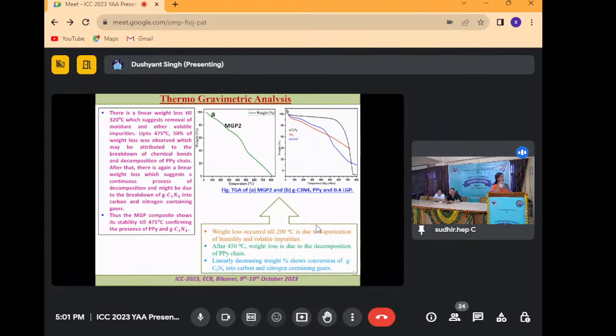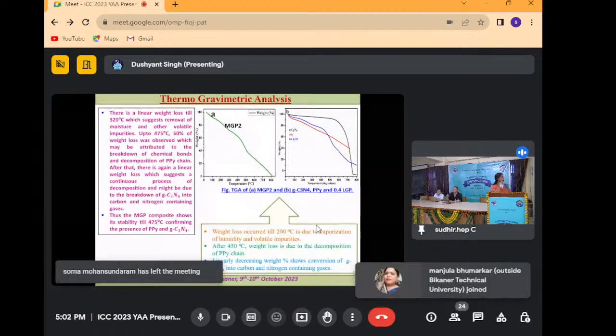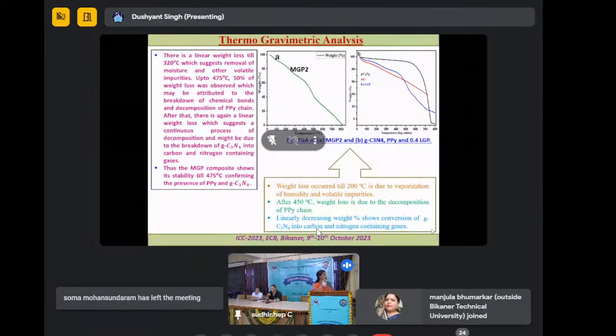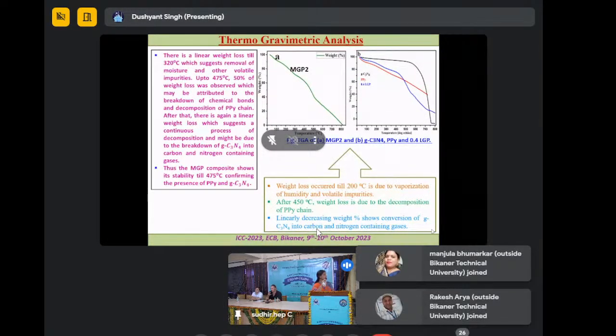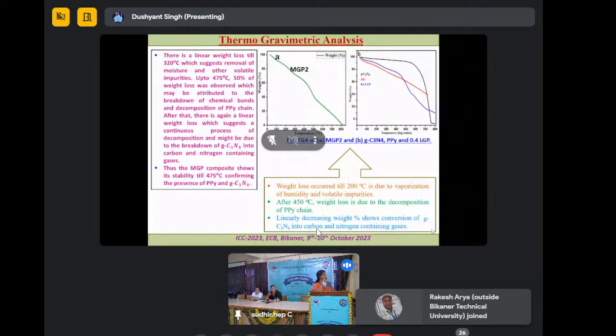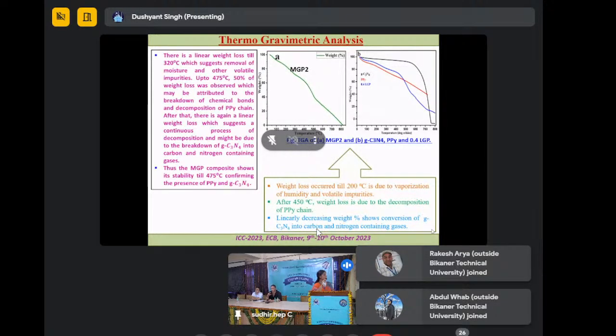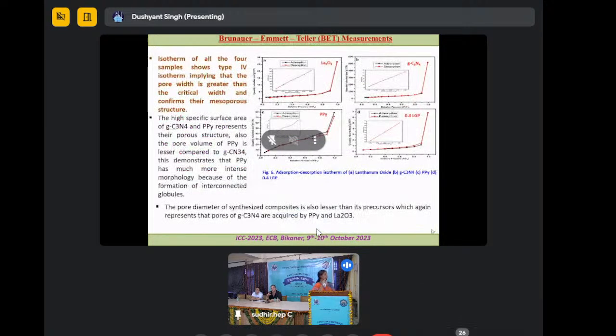And these are the TGA results, which show the thermal stability of these nanocomposites, how and at what temperature LGP and MgP are thermally stable. So weight loss occurs till 200 degrees centigrade in LGP nanocomposites. In graph B we can see that after 450 degrees centigrade weight loss is due to the decomposition of the polypyrrole chain. And in the MgP composites we can say there is stability till 475 degrees centigrade. It is confirming the presence of graphitic carbon nitride in these MgP components.